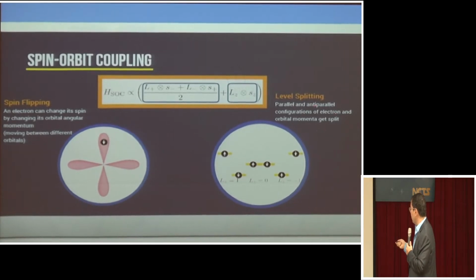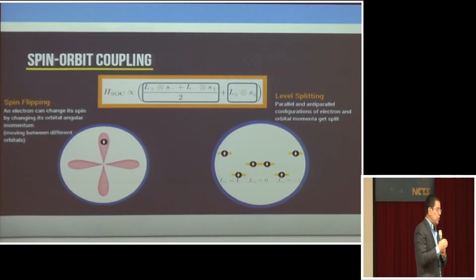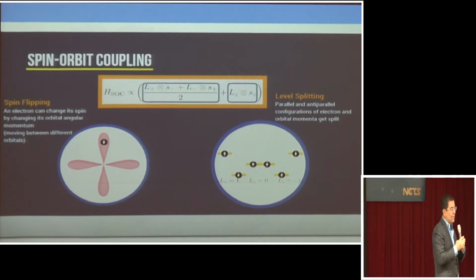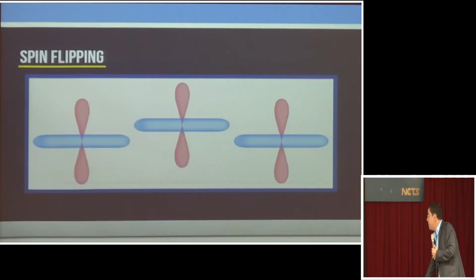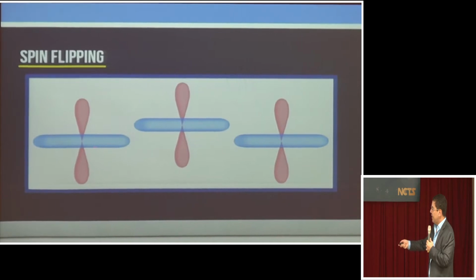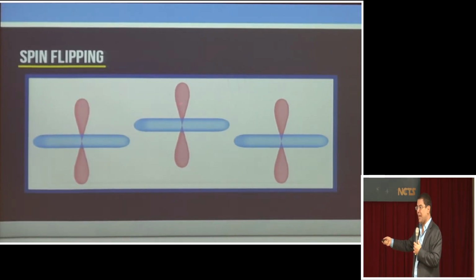And the other part of the spin-orbit coupling, which is this L_z, the z component of the angular momentum, and the z component of the spin, essentially split the energy states depending on the relative orientation of the spin. So these are the two major components in a spin-orbit coupling. Now, when you have these materials, they are not in the same plane. One atom is in the lower plane and the other atom is in the upper plane. So these orbitals are not aligned. Electrons, when they move from orbital to orbital, go through non-orthogonal orbitals in the system.